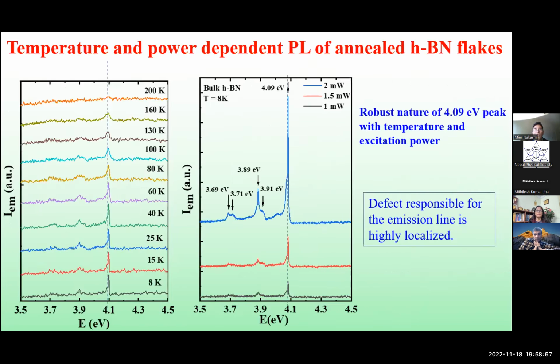After that, we explored this emission a little more. We measured the photoluminescence of the sample at different temperatures, varied from 8K to 200K. The intensity decreases, which happens in most materials because of thermal quenching, but the energy peak position remains the same.